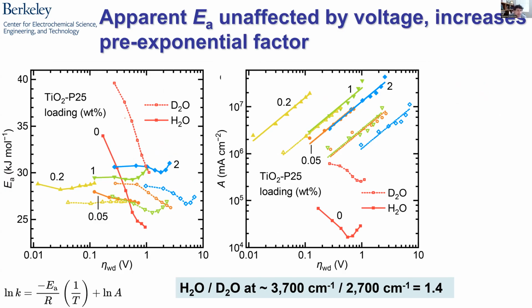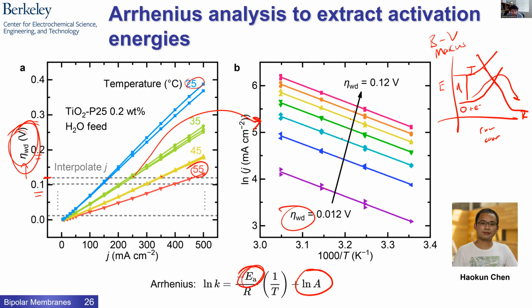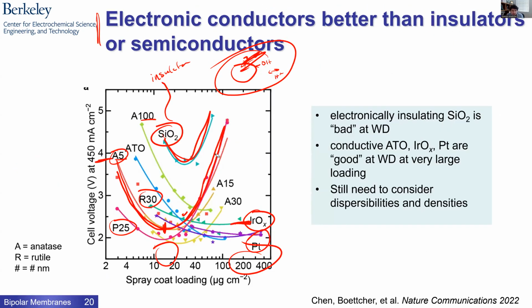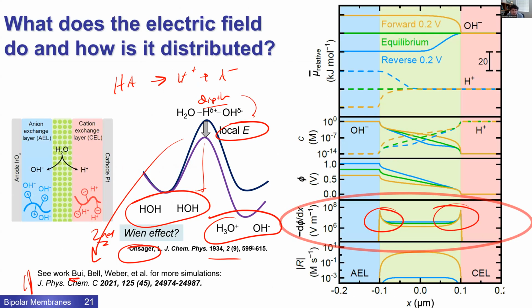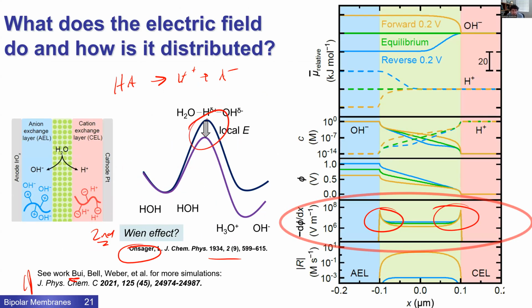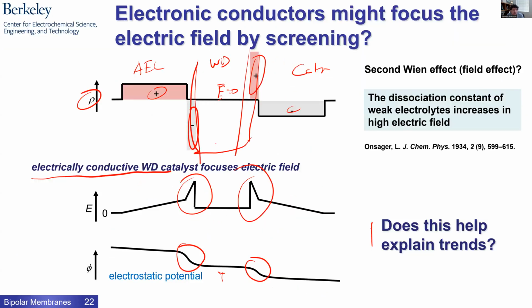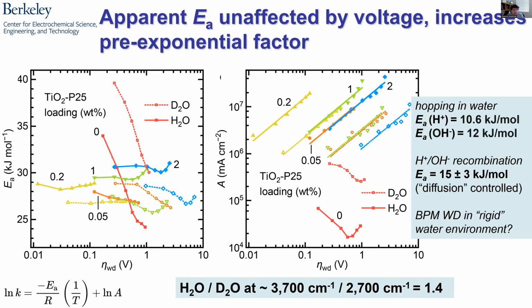Well, we went back and we made systems that didn't have any catalyst, okay? By the way, the Wien effect, if this was the mechanism by which the voltage, the electric field, made the reaction faster, we would expect to see a change in activation energy. So we went back and we made devices with no catalyst, and then you measure the activation energy. I mean, these are terrible bipolar membranes. You need very large voltages to drive any significant current. But what you find is the measured activation energy is, in fact, independent of the driving force. So you are really lowering that activation barrier.